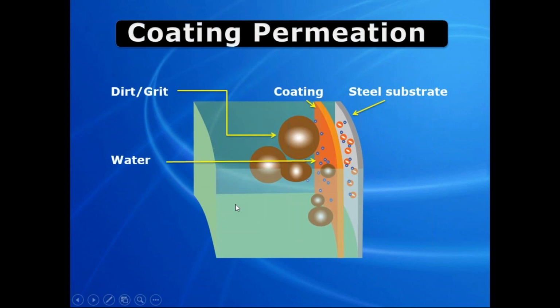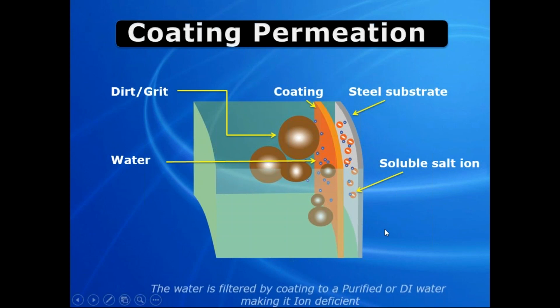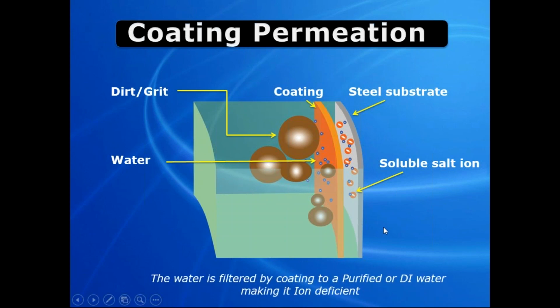On this drawing here, forgive me, but the only thing I don't like is the huge boulder-looking images of dirt and grit. But all in all, it is a good example of what happens with moisture permeation within the coating. Say this orange is the coating and you've got your steel substrate there. If you have moisture penetrating through the coating and there are no salts on the background, it just comes right back out, and there's no corrosion taking place. The dirt and the grit, of course, cannot travel through the coating because it's not hygroscopic. But once moisture goes in and finds these soluble salts, then the corrosion process takes place, and it will continue because abrasive blasting will not remove it from the substrate.